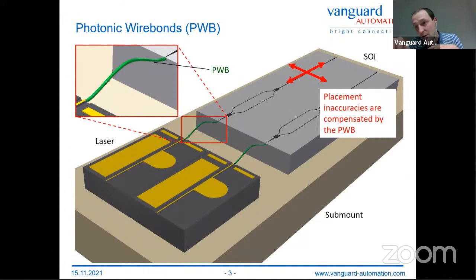So if you're using a high-speed die bond, like you know from electronics, it maybe has 10, 20 micrometer accuracy. So you have a misalignment of say 20 micrometers, our photonic wire bond can compensate this. So you have a simple task to assemble the chips. You can do this really fast, and we're then solving the assembly challenge by 3D printing something to it, and at the same time matching the mode field and doing all the rest.